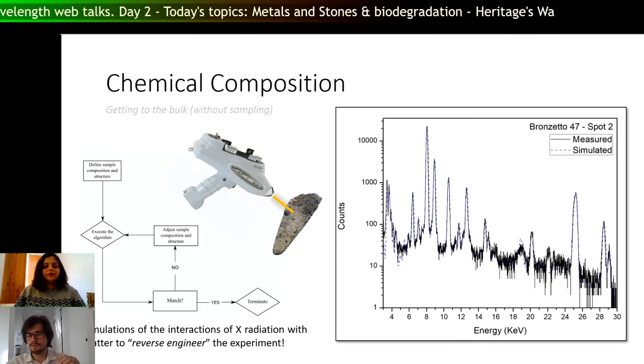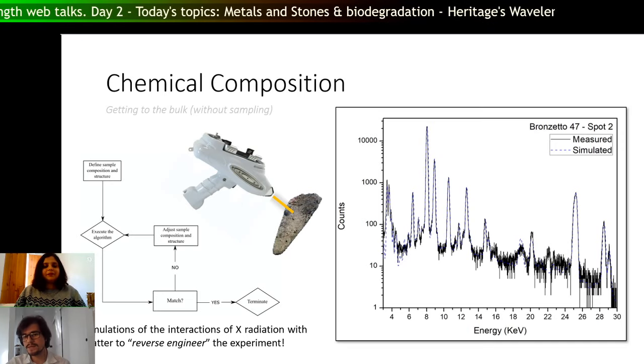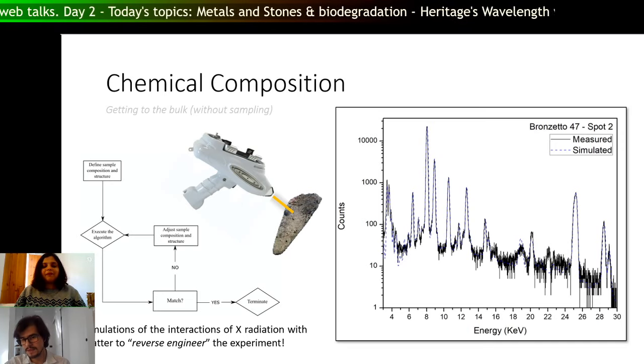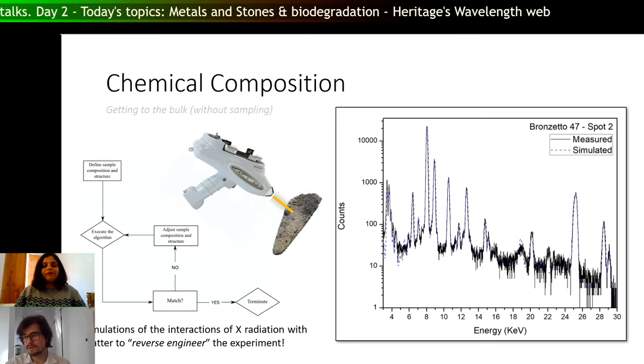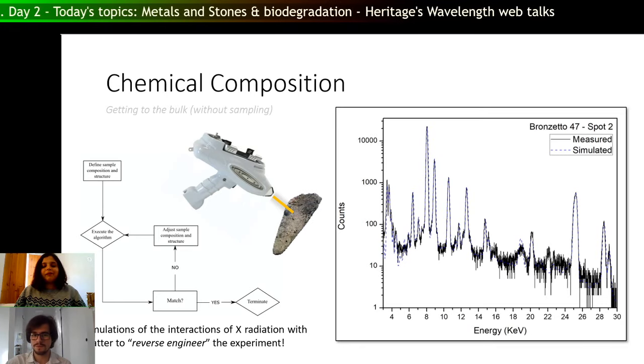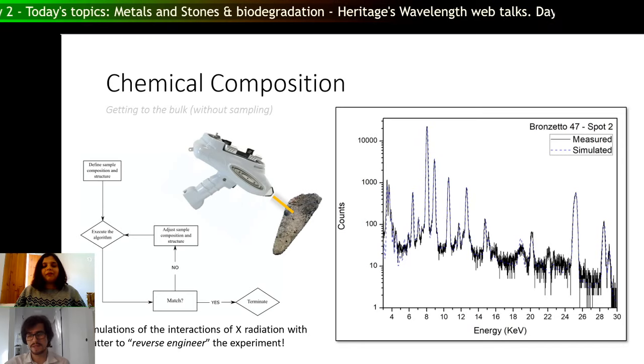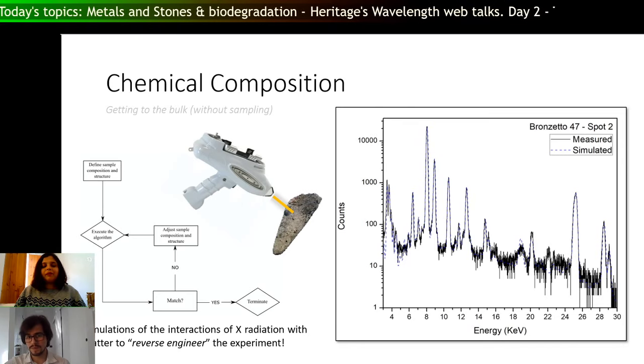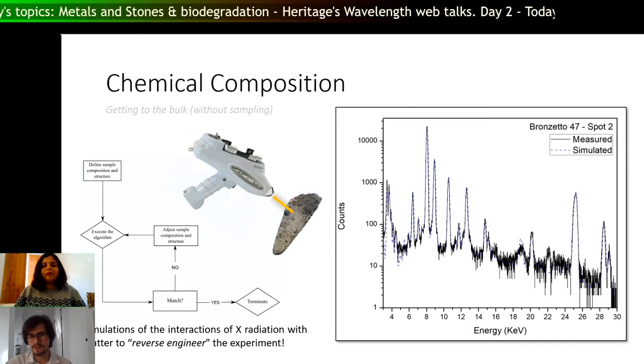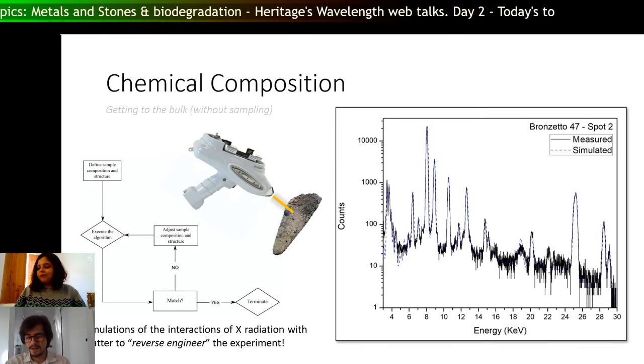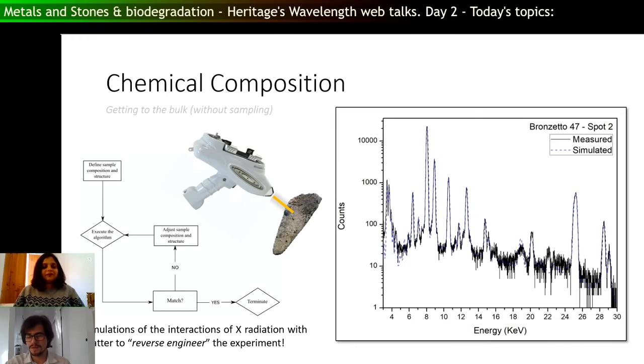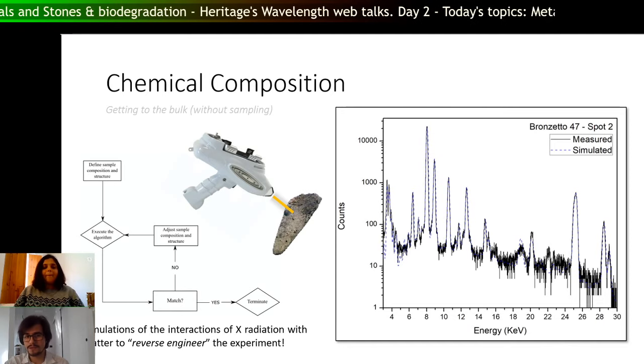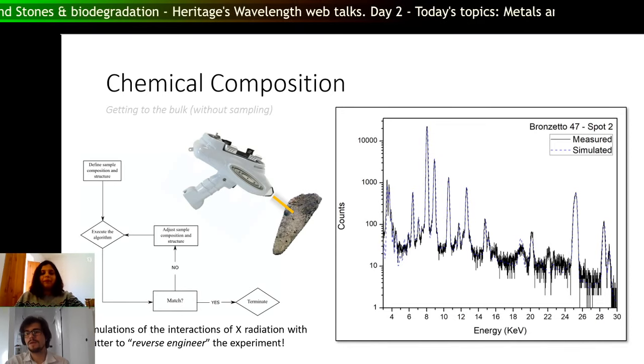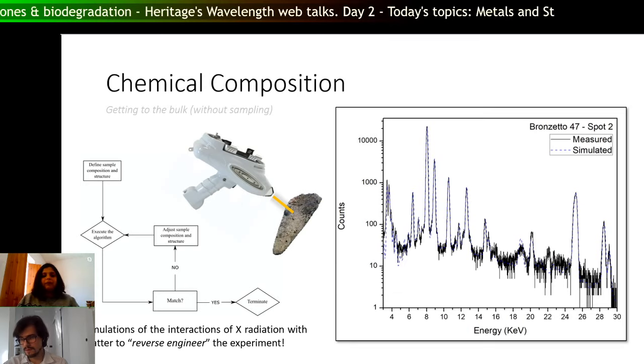And then you'll give this information to your computer. So please simulate a spectrum with these parameters that are equal to the experimental ones, like the distance from the sample to the system, to the X-ray source and the detector. All these parameters must be known because they are physical parameters of the experimental setup. You will give all this information to your computer and tell it to run a simulation. It will give you an XRF spectrum back.